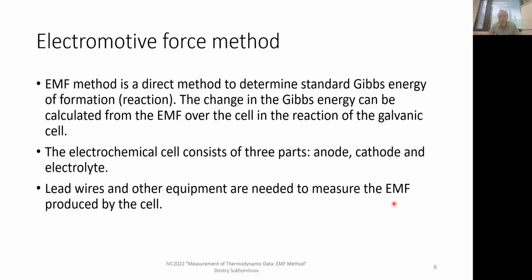Yes, so the electromotive force method is a direct method for Gibbs energy of formation and reactions, as has been said. The change in Gibbs energy can be calculated from the EMF measured and the charge generated over the cell in the reaction happening in the galvanic cell. And we design the galvanic cell in the way we want, so we basically know what reaction is happening there. A galvanic or electrochemical cell is comprised of three main parts: its anode, its cathode, and its electrolyte.